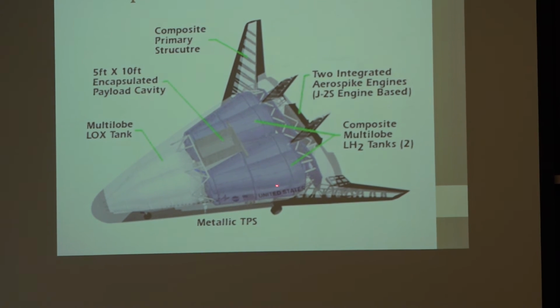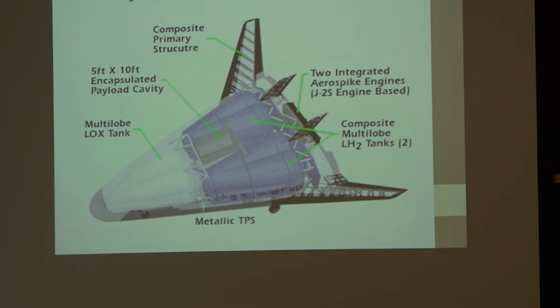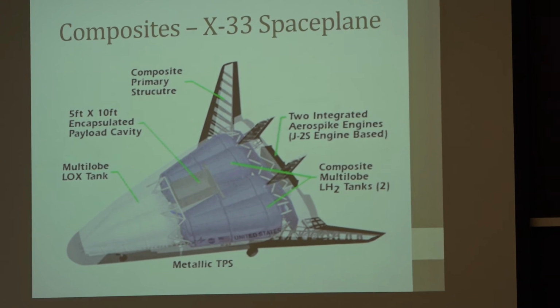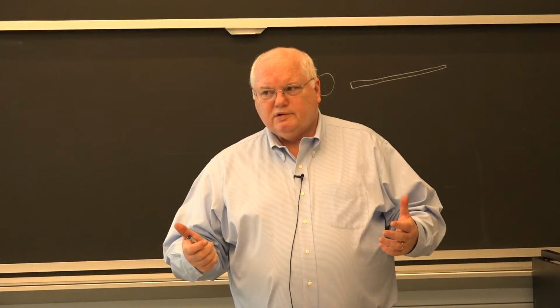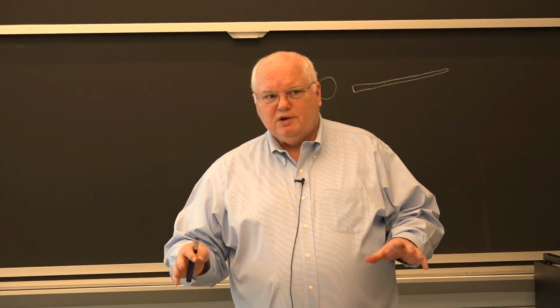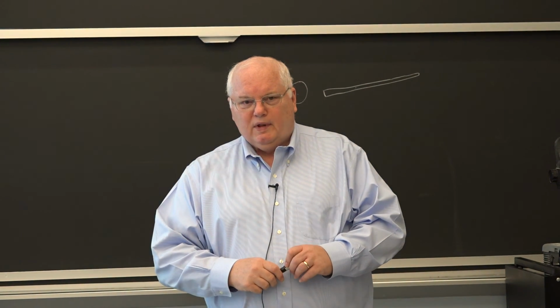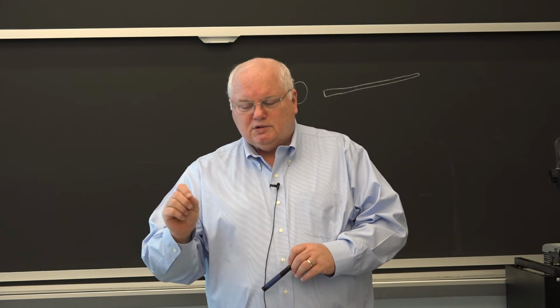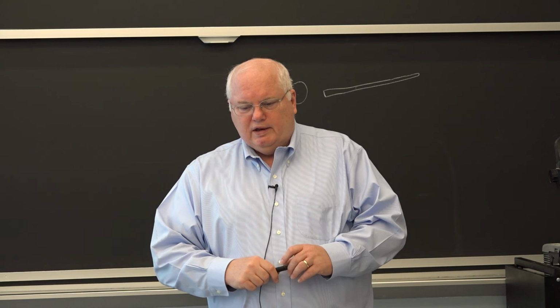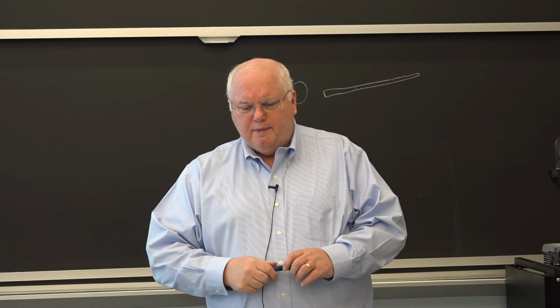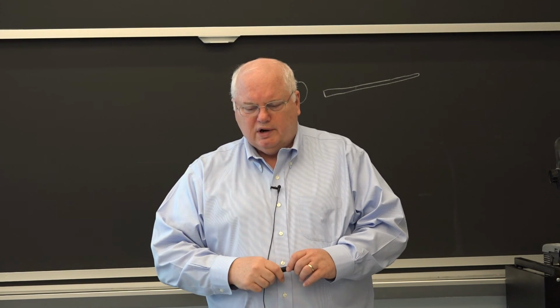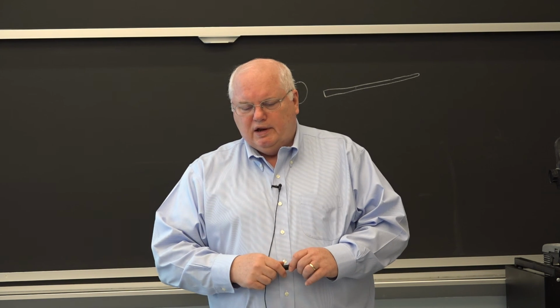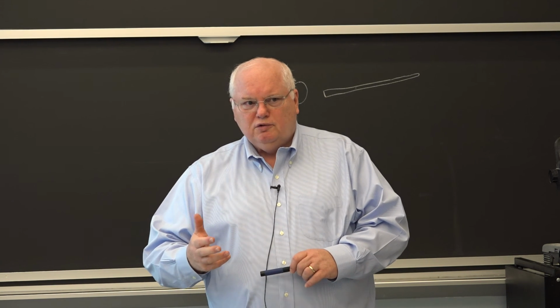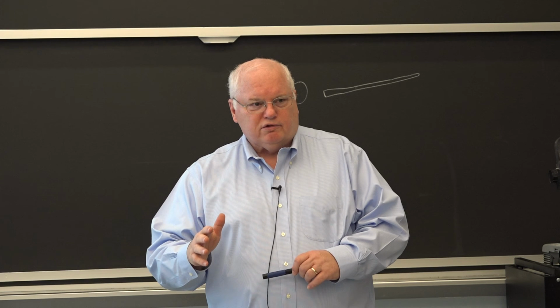And so they decided to build 10 of these lobes, and they put them in the autoclave, heated them up, and 2 of them were junk, and a couple of the others had some delaminations, and it wasn't a good day. So they sharpened their pencil, and they measured the strength of these delaminated areas. They could measure them with ultrasonics and stuff. And they decided instead of a safety factor of 2, they had a safety factor of 1.05.